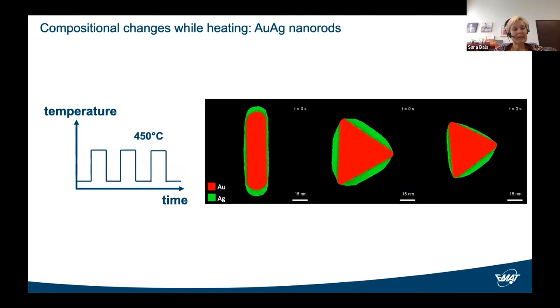So the experiment is the same as before. We're going to heat, in this case, to 450 degrees Celsius. We keep it there for 30 seconds. Then we quench, we acquire a fast tomogram, and then we perform the quantification. We heat, quench, fast tomogram. And so here are slices, quantified slices through the three-dimensional reconstruction. And you can indeed see that we can follow the alloying process.